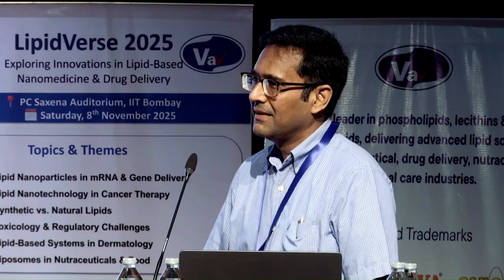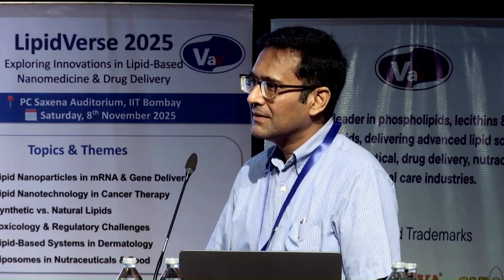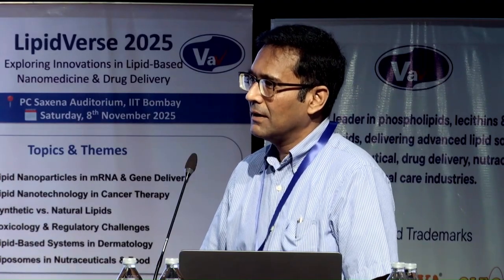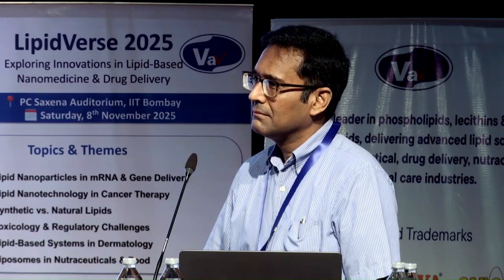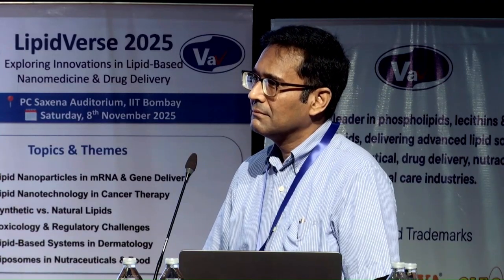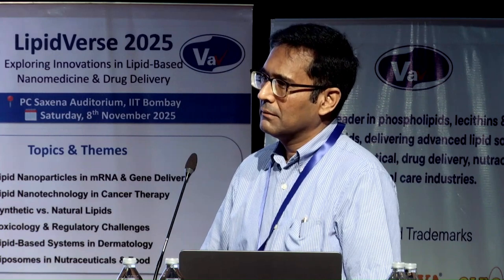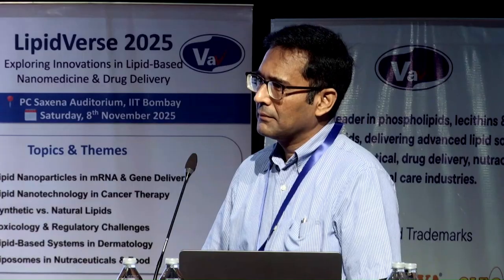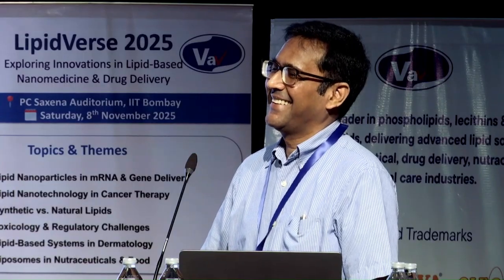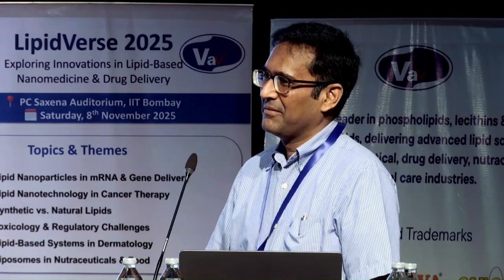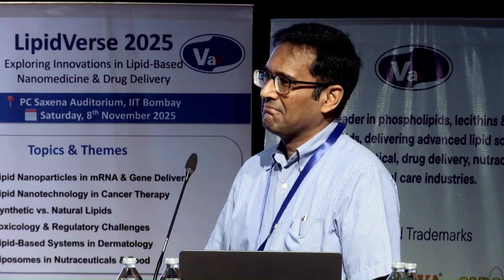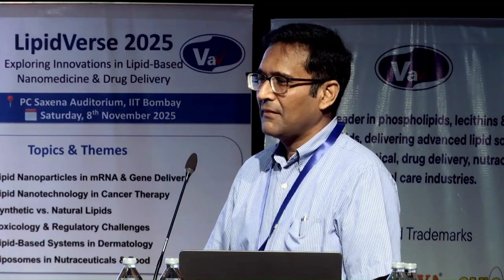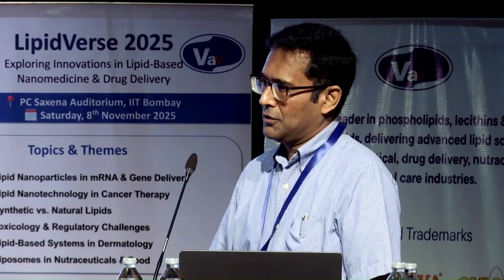The second comment is that when we talk about size reduction, just one word of caution. If you have a content exceeding 20% of nanoparticles less than 80 nanometers, then the US FDA has a very, very stringent guideline on those nanoparticles. So going much below 100 can be extremely counterproductive from the regulatory point of view. And frankly, I don't see any big advantage going much below 100. I mean, between 120 and 80, what's the advantage? I agree with that.